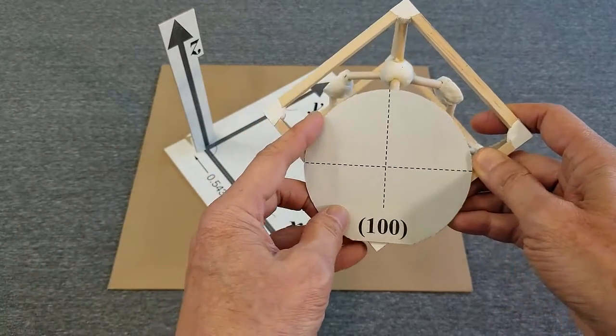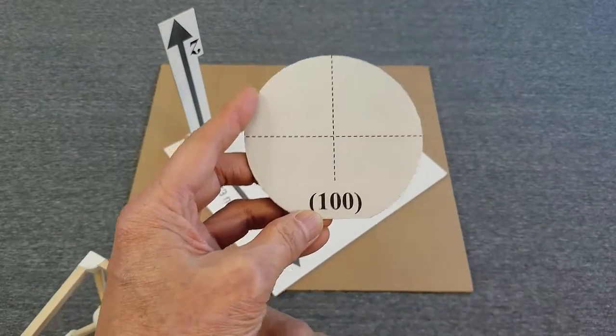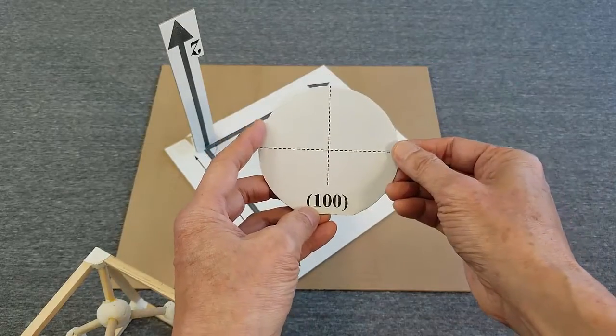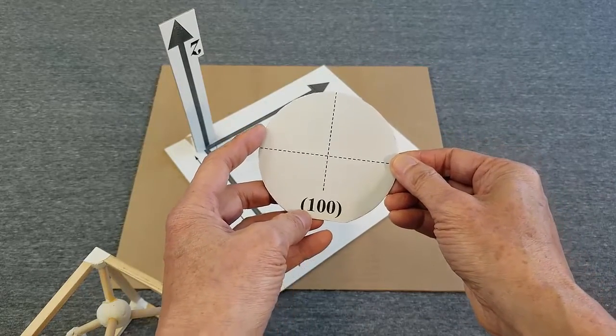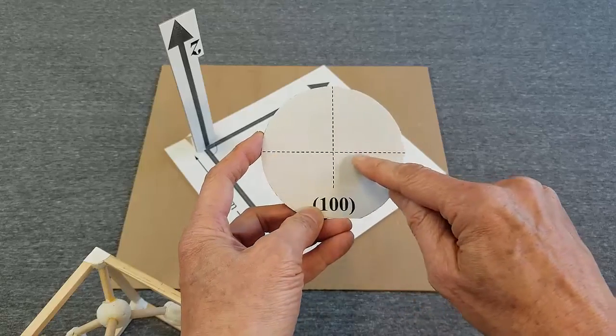Wafers are made with a notch or a flat portion aligned with the rows. If you strike a 1-0-0 wafer with a sharp object, it fractures along the atomic rows and columns, forming pieces with edges at 90 degrees.